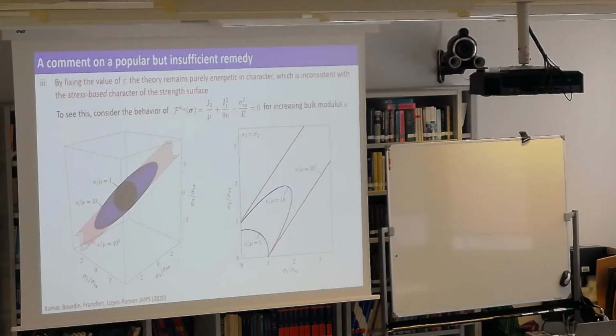And this is essentially because at least for this specific case, you have an energy that is going to zero. If you have a material that becomes incompressible and you apply hydrostatic loading, we know that the energy goes to zero as 1 over kappa. The stress goes to a constant. So when you become incompressible, you have no energy in your system, you only have stress. And that's essentially what is happening here, right, for this type of calibration. Okay, so there are these 3 issues. But the idea, you know, I think this kind of result was very telling, or at least very encouraging.